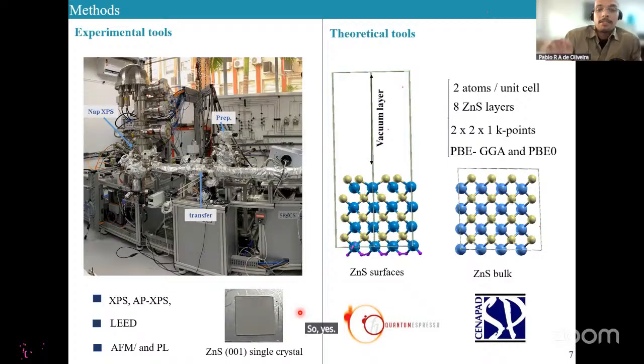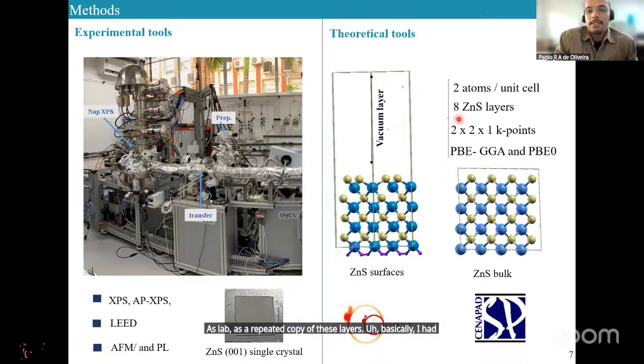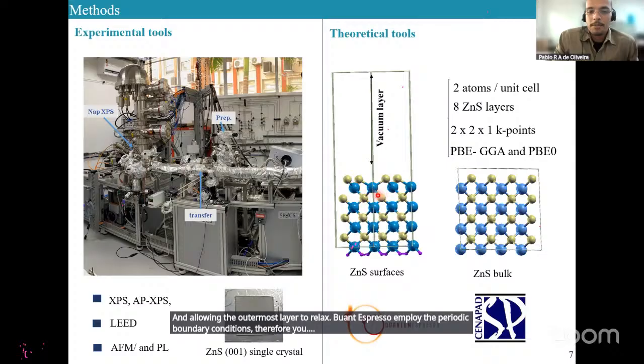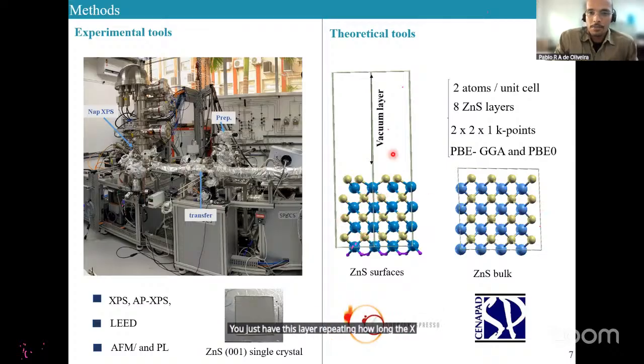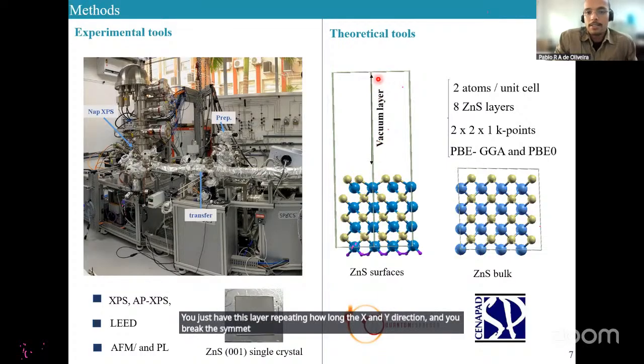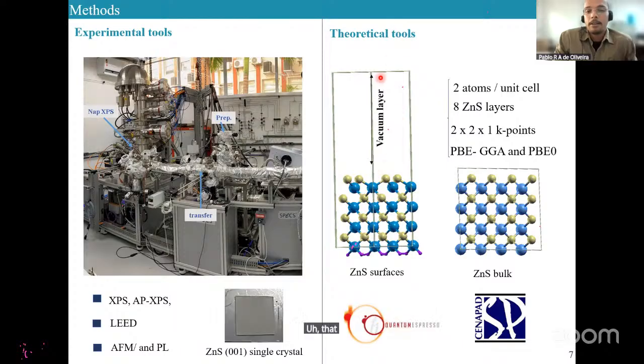So you can address point to point the modification at the surface as a function of the preparation conditions. From the theoretical point of view, the ZnS surface is a slab, a repeated copy of these layers. Basically, I worked with 8 ZnS layers, keeping the bottom one fixed to mimic the bulk properties, and allowing the outermost layer to relax. Quantum ESPRESSO employs periodic boundary conditions. Therefore, you have this layer repeating along the X and Y directions, and you break the symmetry along the Z direction by adding a vacuum layer that avoids fictitious interaction between these layers.